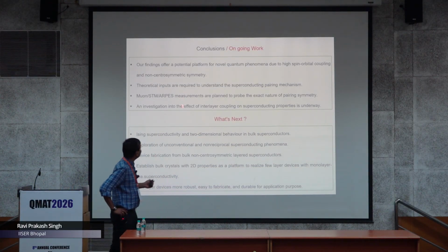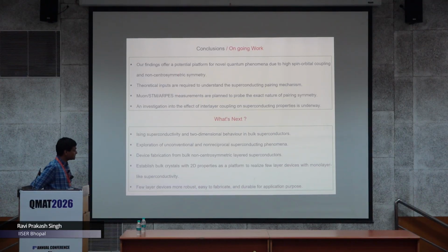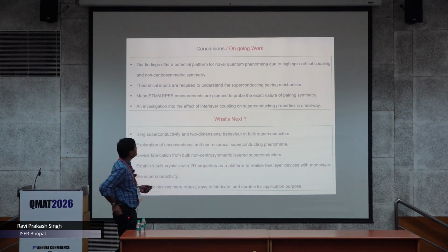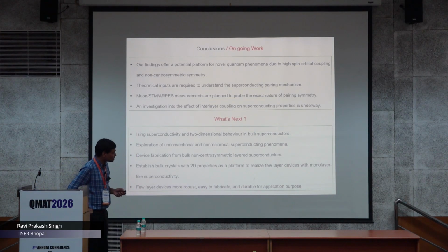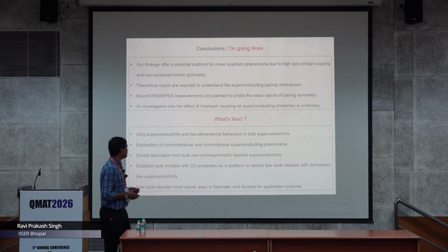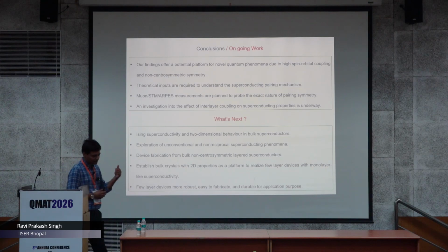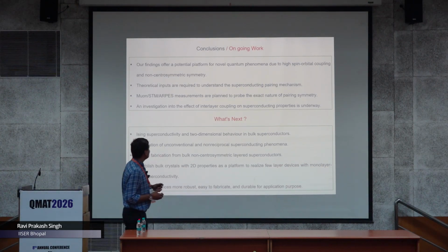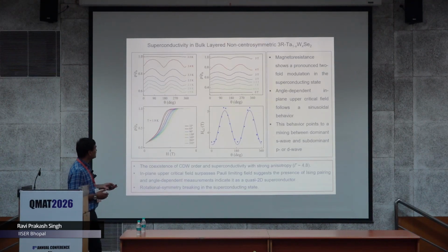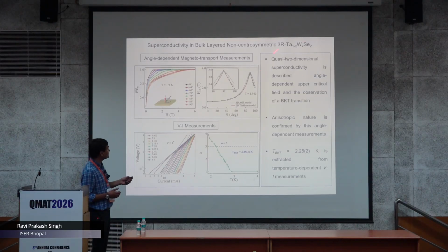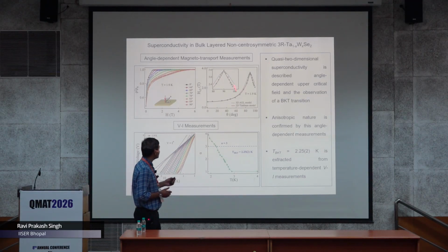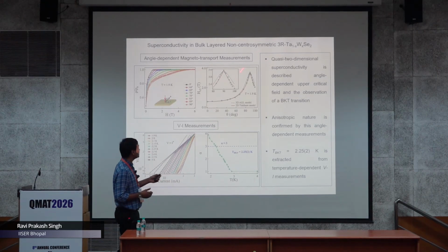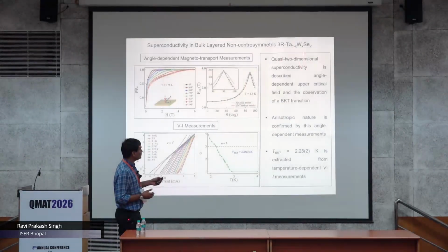So I can say that our finding suggests that this non-centrosymmetric material with high SOC can be a novel platform to realize a lot of unconventional features. And also, by doping this one, like we found in another compound, doping and intercalation sometimes make the 3D interlayer coupling very weak, and you can realize this 2D behavior.